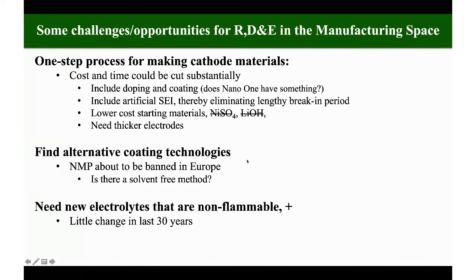And there's a number of other issues coming up. Almost all the cathodes use the organic solvent NMP to make the paste. This is about to be banned in Europe, and I expect if it's going to be banned in Europe, it'll eventually get banned here. And the question is, is there a solvent-free method for making the cathode? Right now, the graphite anodes use an aqueous system, so it's much easier to handle, less toxic, and less need of recycling. So we need to look at this. And really the big issue, we need new electrolytes that are non-flammable. The electrolyte really hasn't changed much in the last 30 years.